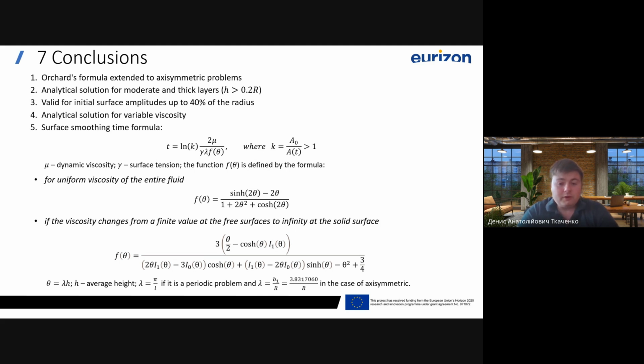The primary goal of our work is to determine the surface smoothing time, which is defined as the time needed to reduce the surface roughness by a factor. Using the derived formula, we can calculate this time considering factors like dynamic viscosity, surface tension, and the surface shape. For surfaces that deviate from standard Bessel or cosine shapes, we can approximate the smoothing time by using the first term in the Fourier series expansion of the surface shape.